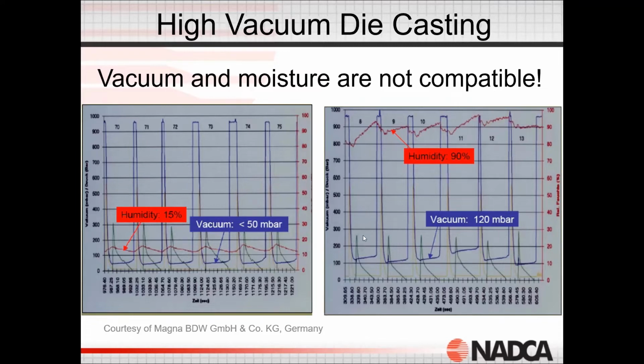So here's the different running criteria. Here we're achieving about 120 millibars of vacuum. Once again, much higher than here. And we can see our humidity level is around 90%. If I were to see this, I would then say, I've got a water leak or I've got excess lube. Any humidity of this level is going to create porosity in our castings. And once again, if we can't measure it, we can't control it.